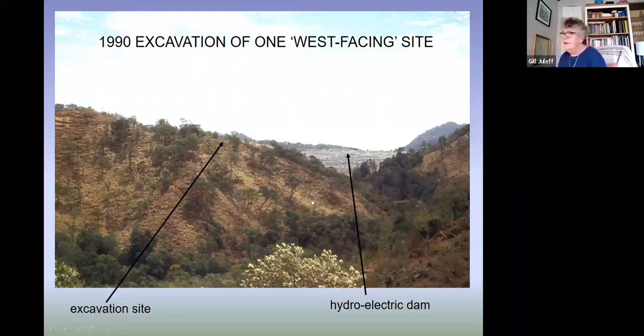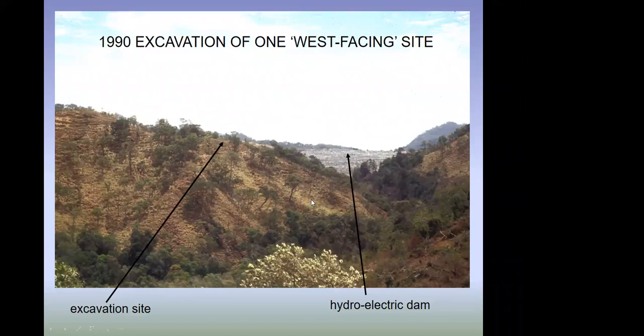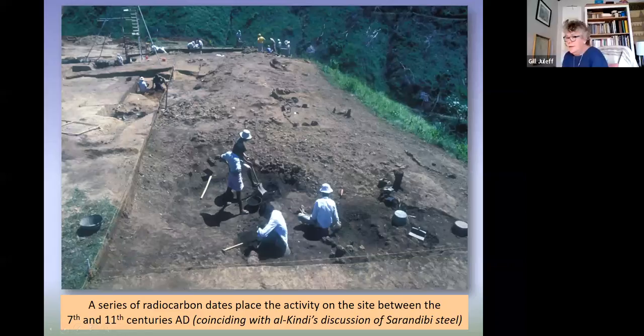Right, sorry. This is the site that we excavated over a period of about 6 months. What you're looking at here is essentially the slag heap. All of the slag, the west is to the right-hand side of the screen. You can see where they're actually digging in the foreground. The soil is very black. That's from the charcoal and the residues coming out of the furnaces. The bigger lumps of material are lumps of slag.